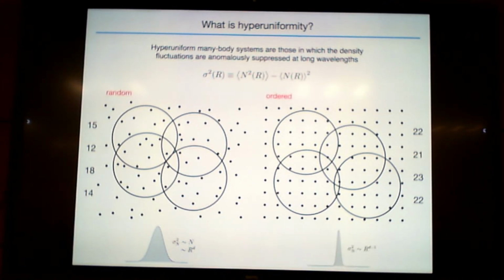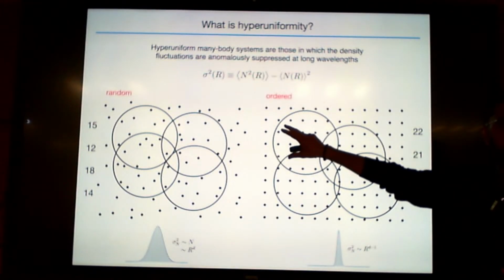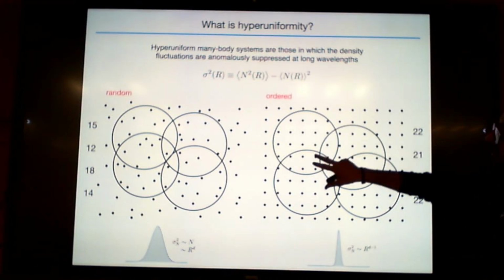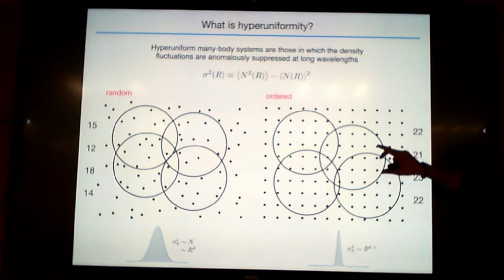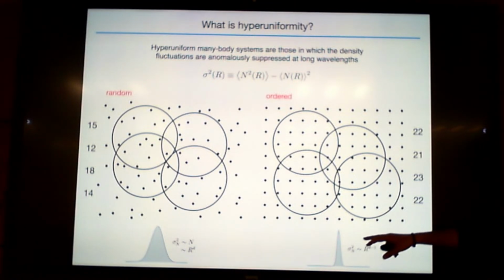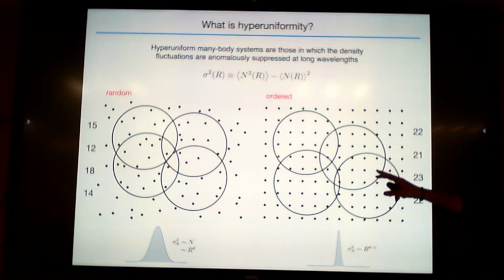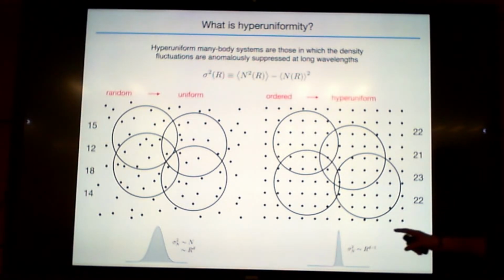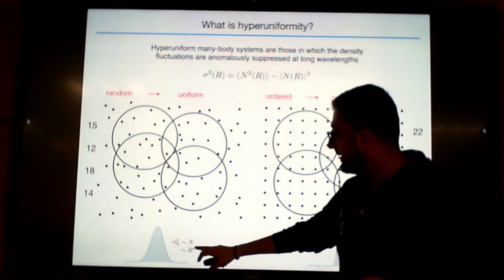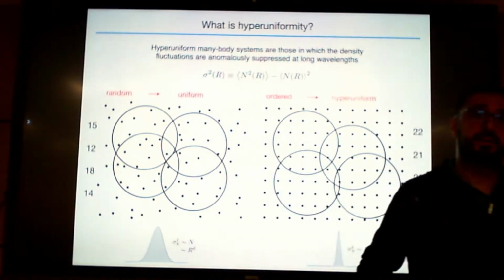On the other hand, since this is more regular, when I keep moving my window here, all the change comes basically from the circumference of the sphere. So it grows with r to the power d minus 1, dimension minus 1, in this case linearly in r. So we say that the system is uniform and that system is hyperuniform. It grows slower than the dimension d in r.